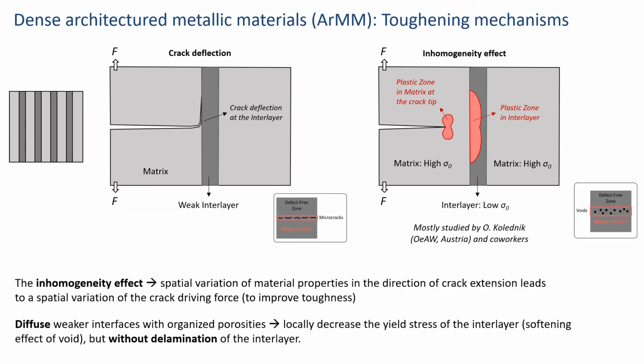So the toughening mechanism that we hope to activate within these materials is a bit different depending on the type of interfaces that we will introduce in the material. In the case of a sharp interface made of microcracks, it's most likely going to introduce crack deflection and interlayers which can serve as crack arresters. But in the case of a diffuse interface, what we are hoping to see is also the inhomogeneity effect.